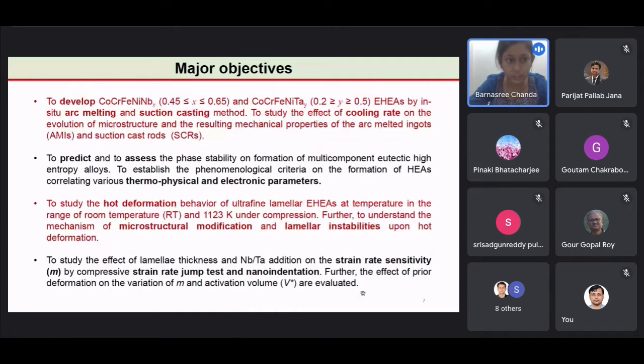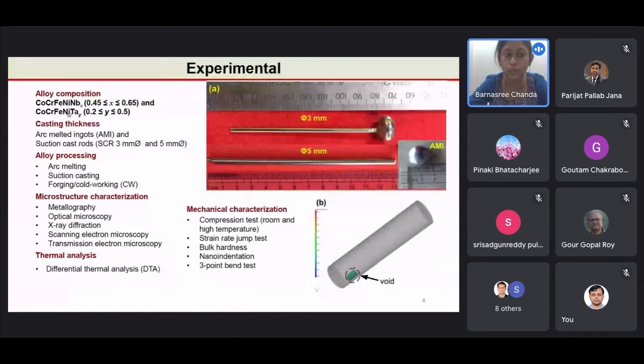So, two series of alloys have been developed, that is cobalt chromium iron nickel niobium and cobalt chromium iron nickel tantalum, by arc melting, suction casting, forging, and cold rolling. Henceforward, we will denote arc melted ingot as AMI and suction casted rod as SCR. Further, microstructural characterization and thermal analysis have been done, followed by mechanical characterization. The figure shows the alloys developed in our laboratory: the 3 mm diameter suction casted rod, the 5 mm diameter suction casted rod, and the arc melted ingot.